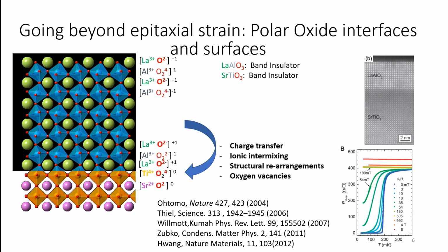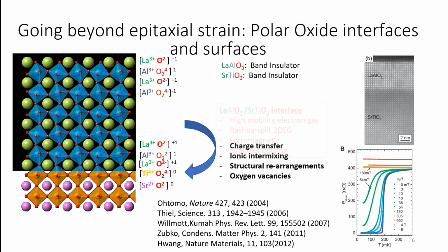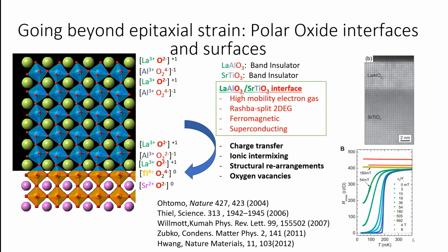But they found that past some critical thickness the material suddenly became metallic. The interface became metallic. And since then, people have found that this interface between these 2 materials, which by themselves are insulating, is actually superconducting at low temperatures. This is at millikelvin, but nevertheless, it's a really cool thing to think of, taking a brick and a piece of wood, putting them together, and having superconductivity emerging at that interface.